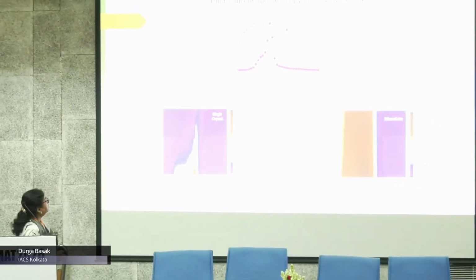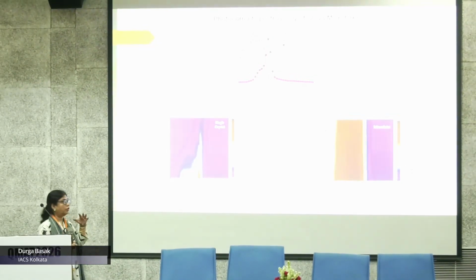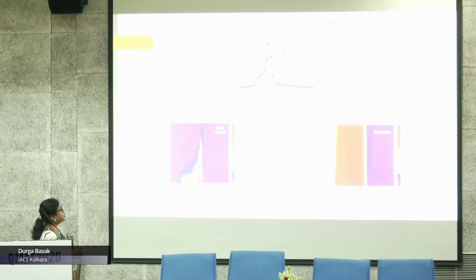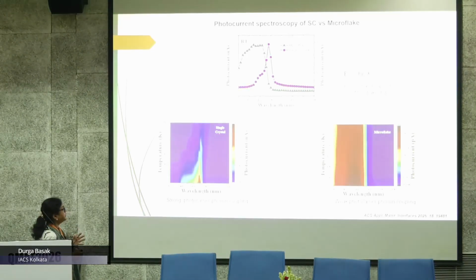So in order to know more about carrier-phonon interaction, we have formed photodetector devices on single crystal, and this is on the microflake. In the single crystal, it was about 194 micron, and for the microflake, the AFM image shows that the thickness of the microflake is almost 80 nanometer. So this photocurrent spectroscopy is very important. It tells you a lot of things about the recombinations or the electron-hole separation.